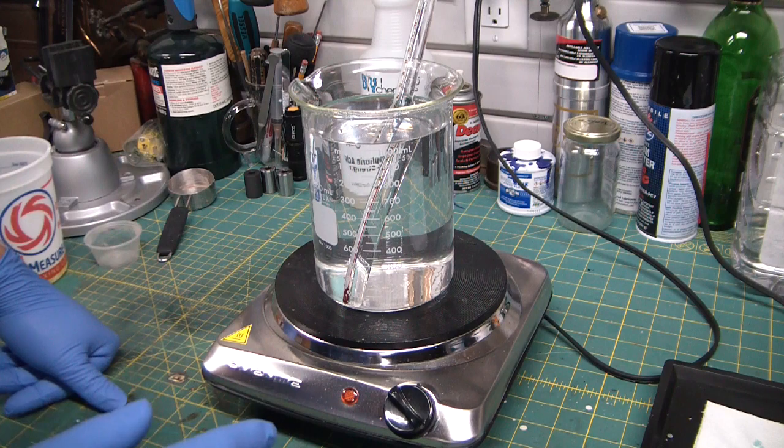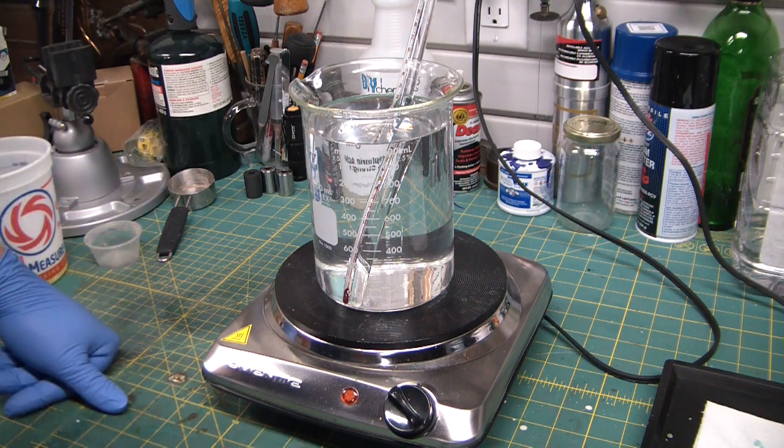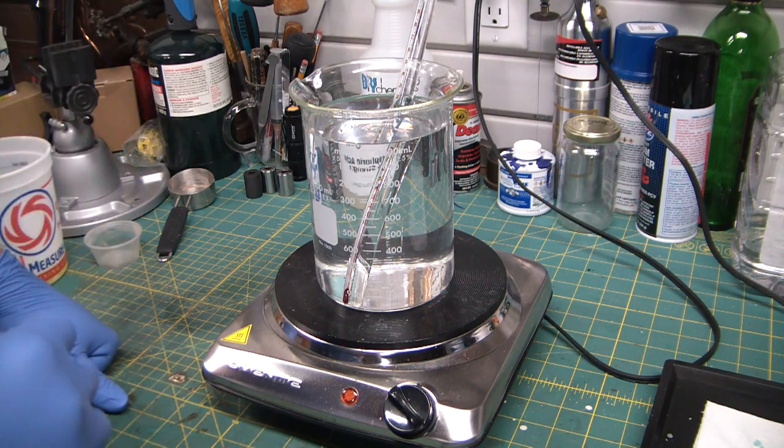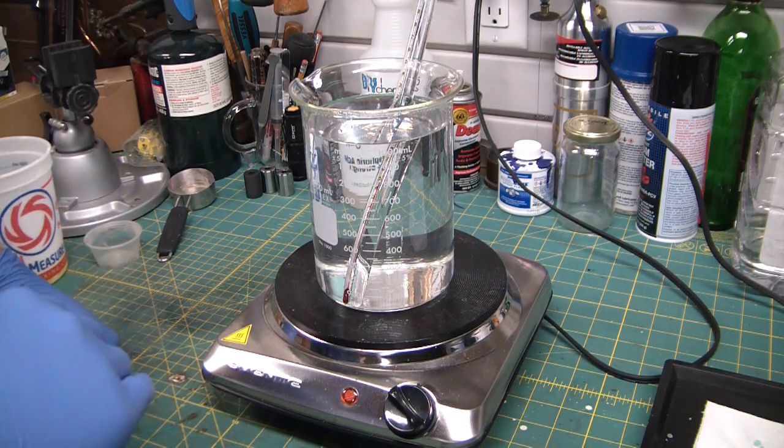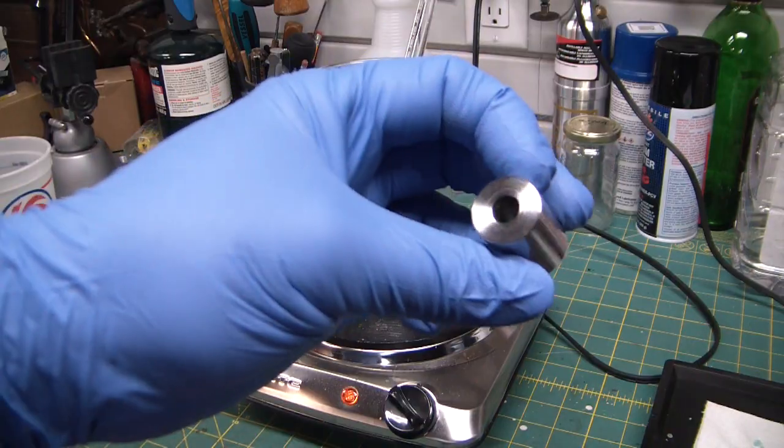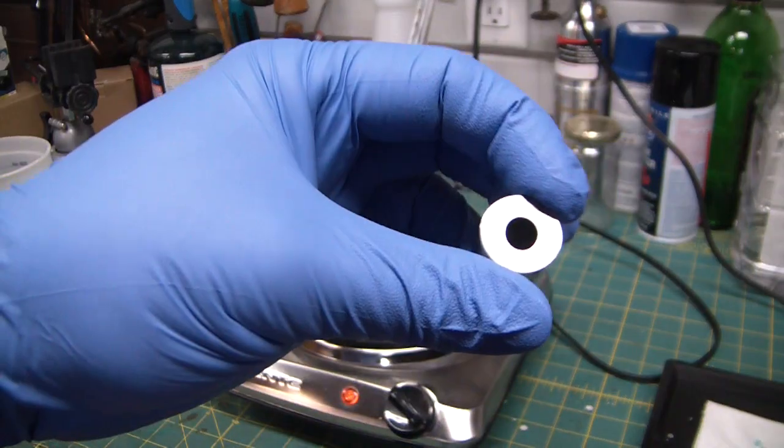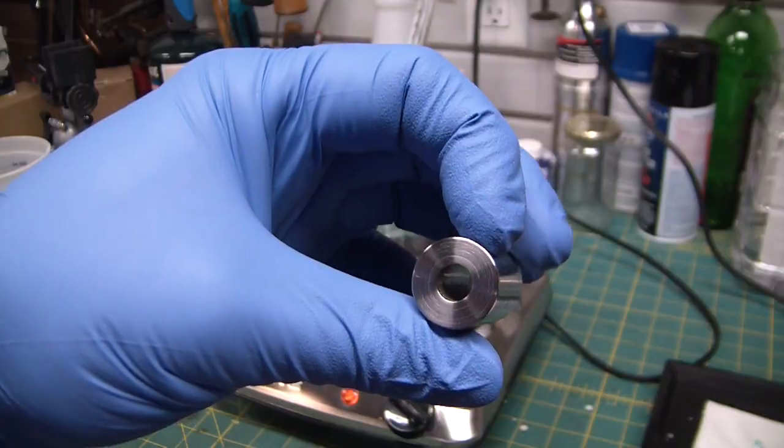Now another trick to manganese parkerizing: it needs to be just under the boiling temperature of water. You can't do it at lower temperatures like you can with zinc parkerizing. So I'm gonna go degrease the heck out of this part, spray it down in all kinds of fun cancer causing compounds.